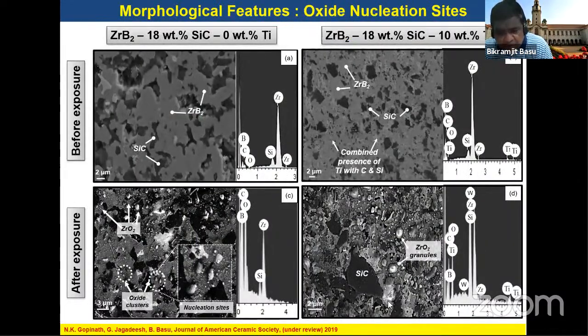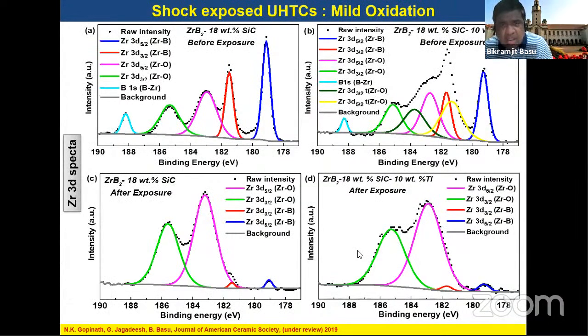Okay, now we have done this hypersonic shock test further on the zirconium diboride based materials. We have found very few nodules of zirconia present after the exposure, and we have subsequently done X-ray photoelectron spectroscopy analysis just to show you that it is zirconium oxide which is present, but this zirconium oxide is essentially a result of the oxidation of zirconium diboride, and its presence is not very, very significant, I must say.